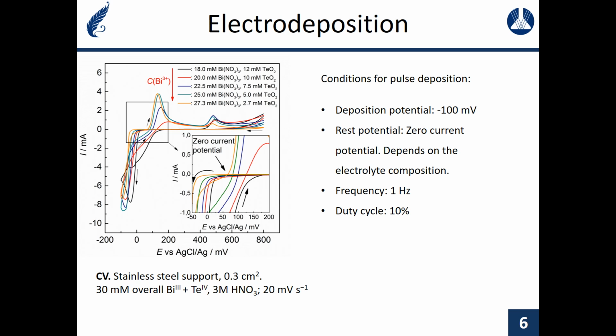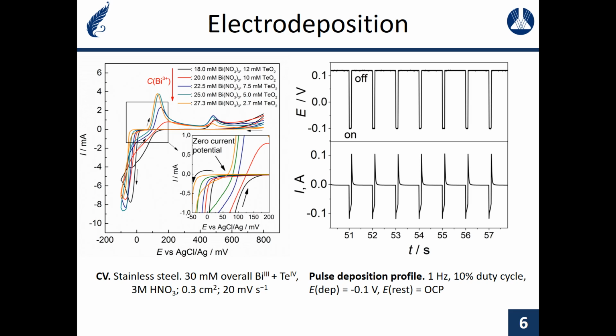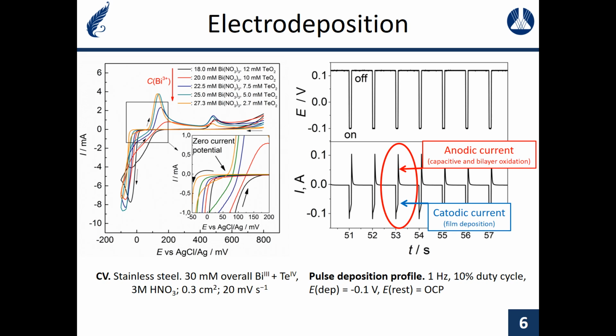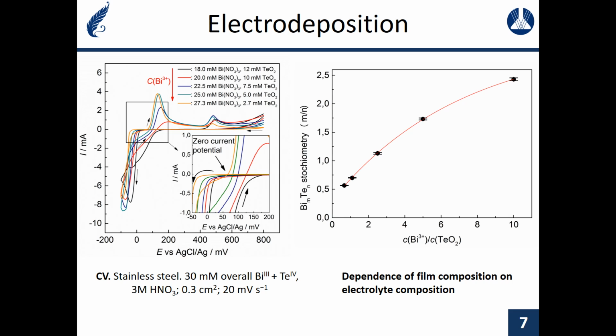For the electrodeposition of the films of bismuth telluride and superlattice structures, we chose the pulsed electrodeposition mode with a square potential wave. Deposition potentials were determined from cyclic voltammograms. Here are the potential and current profiles in the pulse electrodeposition of the superlattice. The cathodic current is attributed to the film deposition. Anodic current prevents nucleation of bulk bismuth and controls bismuth interlayers. The composition of films determined with atomic absorption spectroscopy shows clear dependence on the electrolyte composition, and this provides efficient control of the relative number of the building blocks in the superlattices.